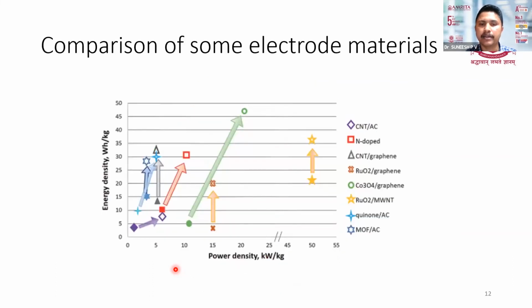Then when we compare the different materials that I have shown in the form of a Ragone plot, I could see that the ruthenium-based material, which is coated on multi-walled carbon nanotubes, is having high power density, as well as high energy storage capacity. And there are other materials, activated carbon, the N-doped carbon, and all these materials are having charge storage capacity and sometimes lack in power density.